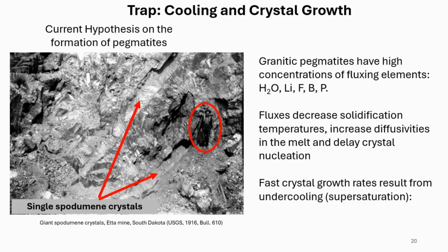The other thing that they do is they increase diffusivities. So you're changing the viscosity and you're increasing the diffusivities. And another thing that the fluxes do is they delay nucleation. So if you have, say, a granite with water in it, I love this. What temperature does water freeze at? Anybody? No. You can take water and put it at 0 degrees, it'll never, ever freeze. Ever. It has to be below the nucleation temperature. You have to be below the solidus. You have to overstep it in order to provide kinetic energy for crystals.